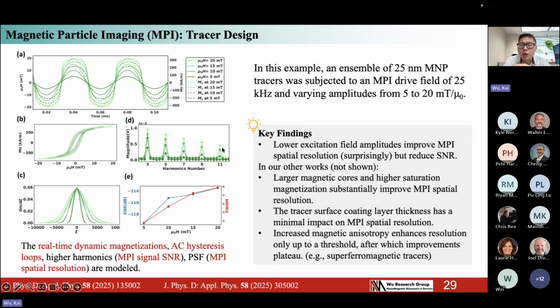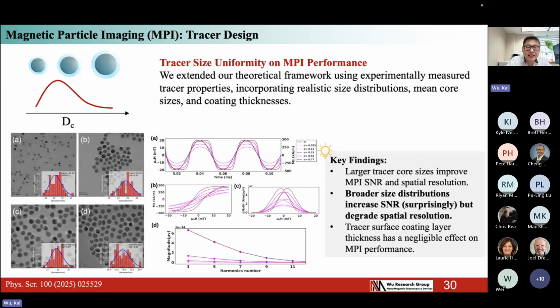So with the consideration of the time, I will just quickly go through these findings. We found that a lower excitation field amplitude will actually improve the spatial resolution of MPI imaging, but it will lower the signal-to-noise ratio for imaging. In other work, we also found that larger particles can improve the MPI spatial resolution based on the steeper magnetization curve in the AC MH loop. And if we have MNPs with higher anisotropy, it will also increase the imaging resolution. One topic the UC Berkeley and the NIST group are working on is using nanoparticle chains, MNP chains, for imaging. This also introduces shape anisotropy to improve the resolution in MPI imaging. We also consider the dipolar interaction between nanoparticles, which may affect imaging quality.